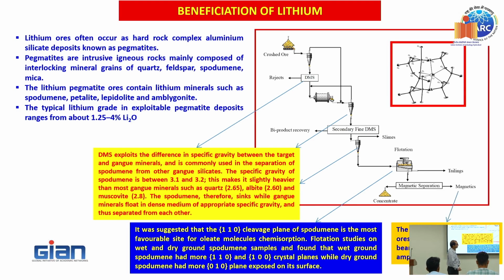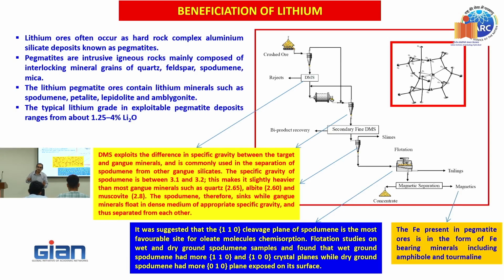After you do that, you have the magnetic separation stage. In this, what we do, we remove the iron-based minerals. That is also present in the pegmatites. Those things are separated out and you get a concentrate which is exclusively rich in the spodumene. So you have done pre-concentration of spodumene by physical beneficiation. Now over. Now you have to extract lithium. How do we do that?